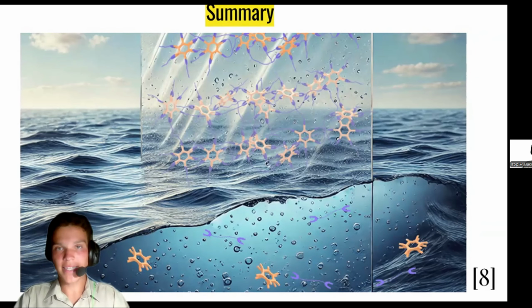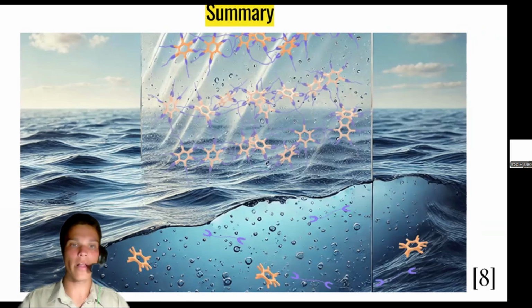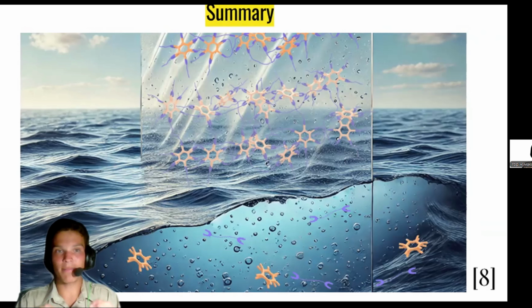The unique feature of this plastic is that under the influence of salt, it quickly breaks down into its original monomers. In seawater, this process takes only 1 to 3 hours, while in saline soil, the material fully decomposes in approximately 8 days. The dissolution happens because the salt water disrupts the chemical bonds between the two monomers, after which natural bacteria complete the decomposition process. As a result, the plastic does not leave behind harmful microplastics, does not release carbon dioxide, and turns into substances that are harmless to the environment.